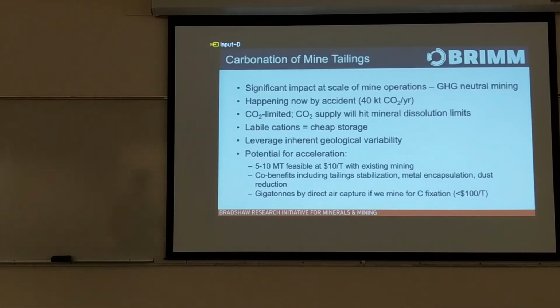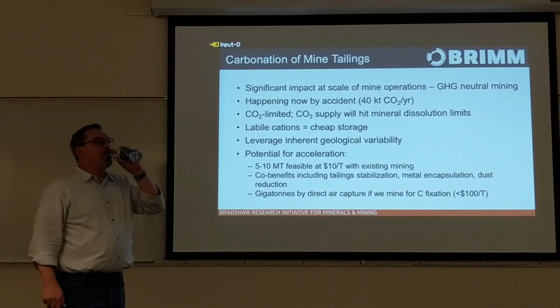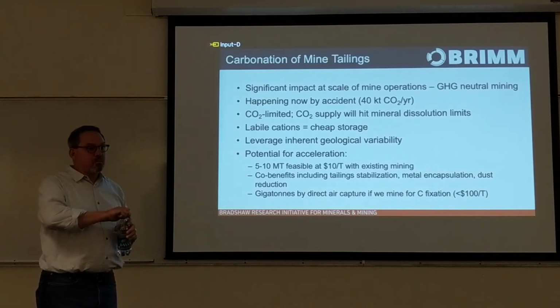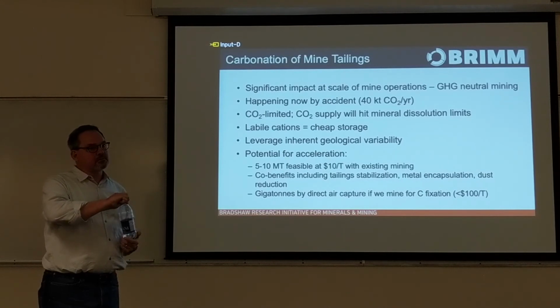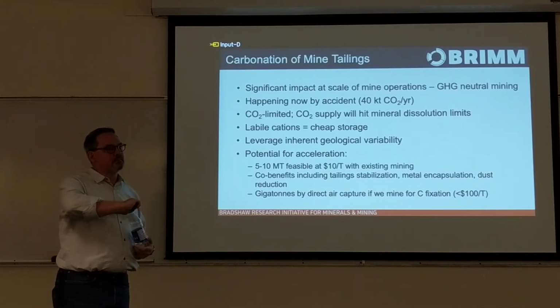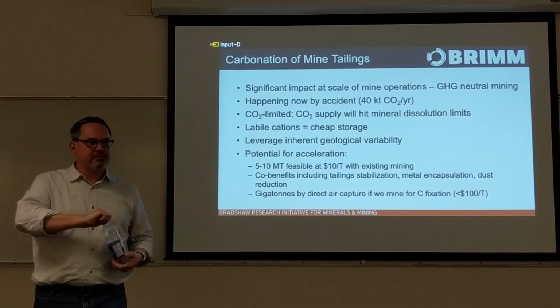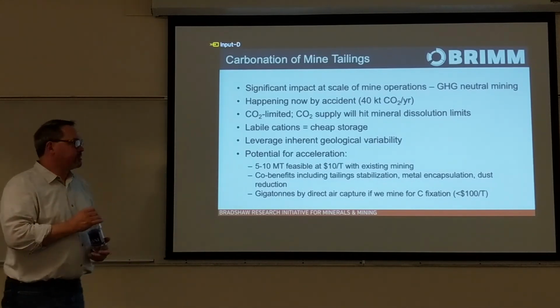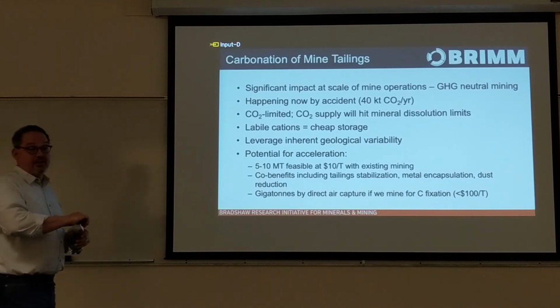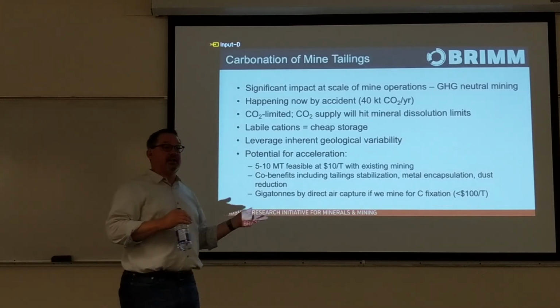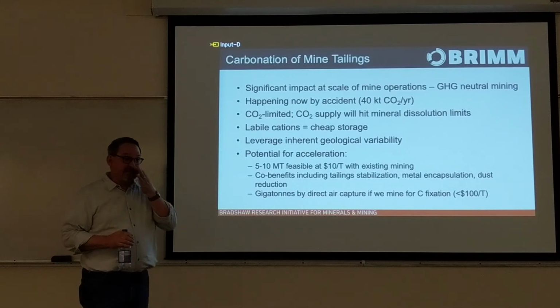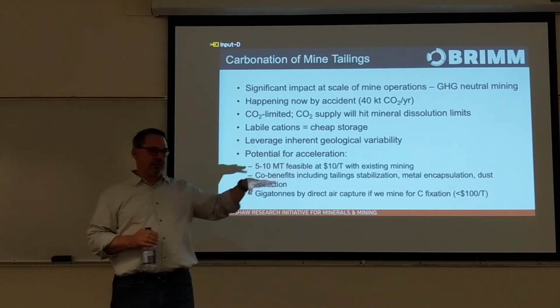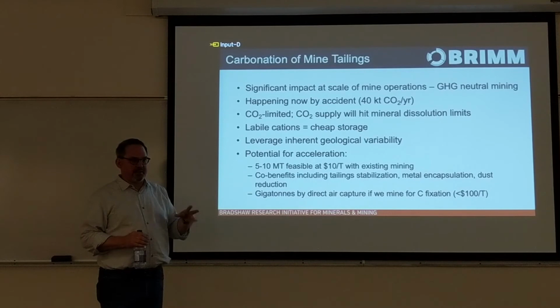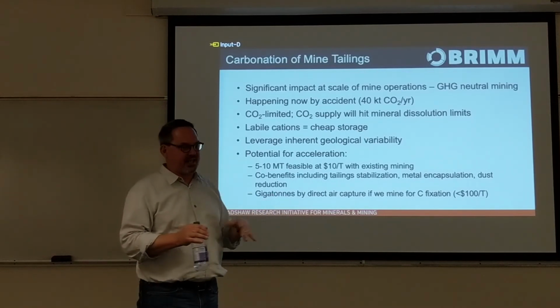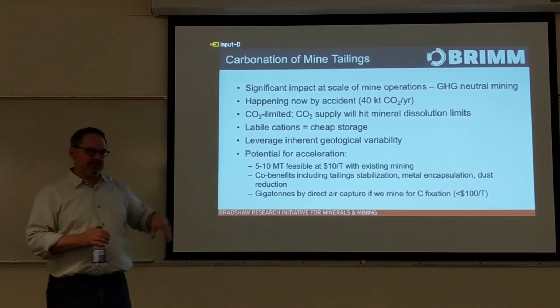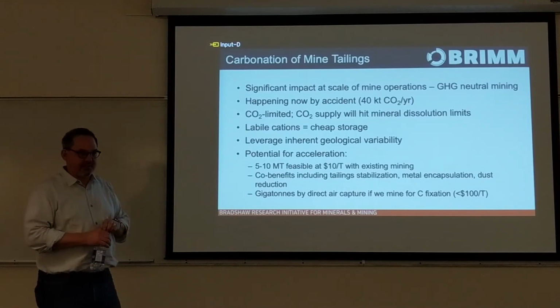If the CO2 supply is 10% at flue gas, when will you hit that mineral dissolution limit in a column in terms of time? So it depends on flow rate and labile magnesium content and preferential flow paths and things like that. But certainly we've done meter scale columns of, not of tailings, but basically mixing. We've used quartz sand as inert framework and mixed in minerals that have labile magnesium at modest levels.